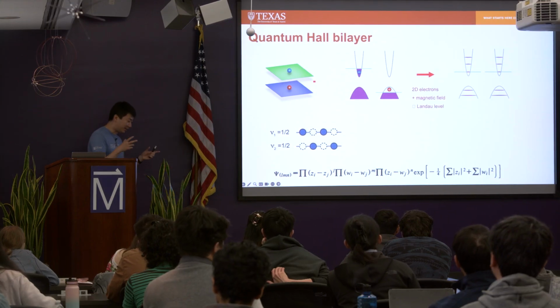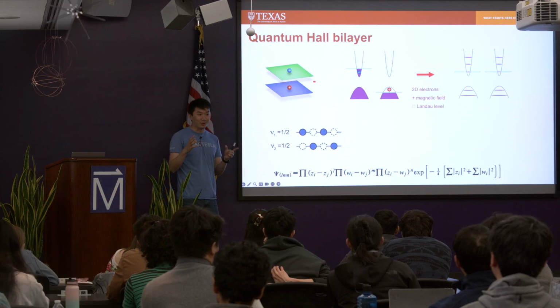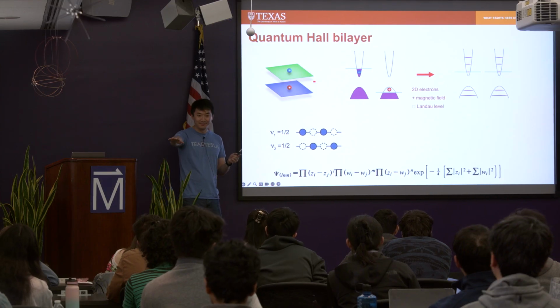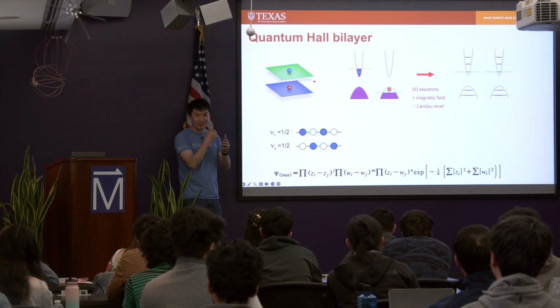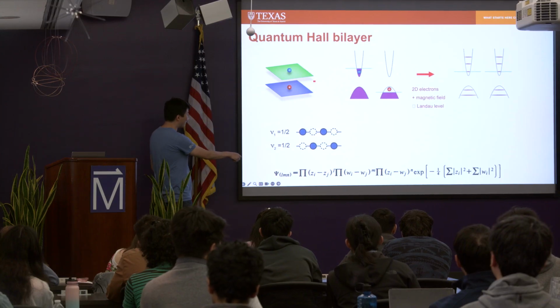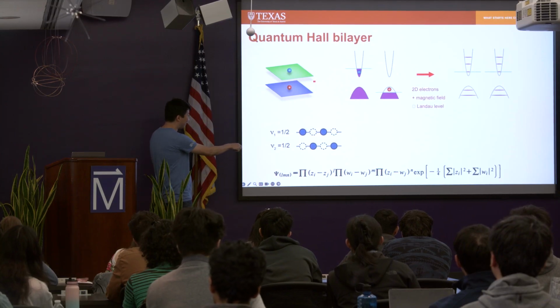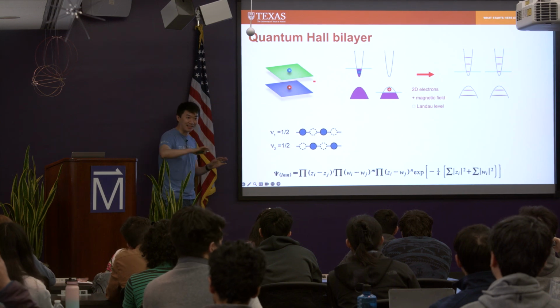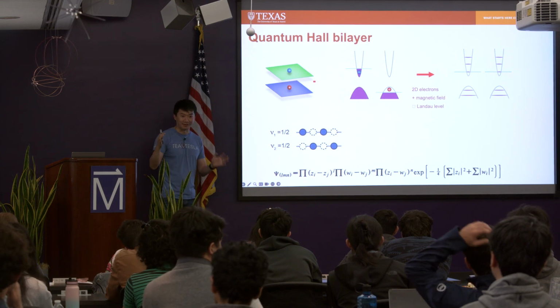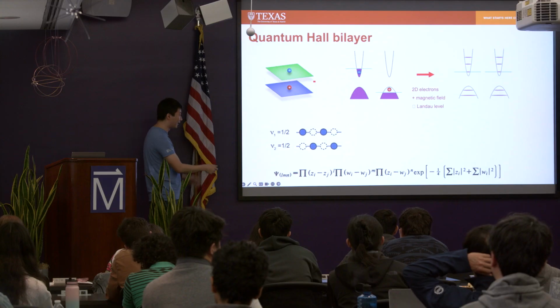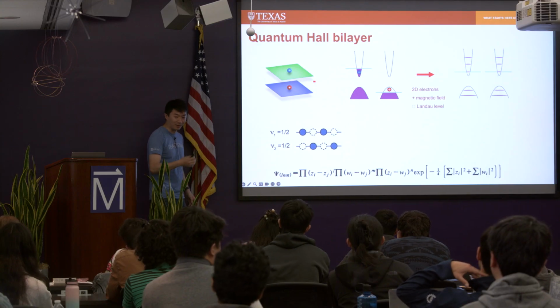You create an integer quantum Hall effect at filling 1 in one layer, right? And then you spread this wave function out to 2 layers evenly, right? So if you just count the electron and ignore the layer degrees of freedom, this is exactly the same as integer quantum Hall effect at filling 1. You spread it out to 2 layers, right? Then you get some kind of interlayer correlation.